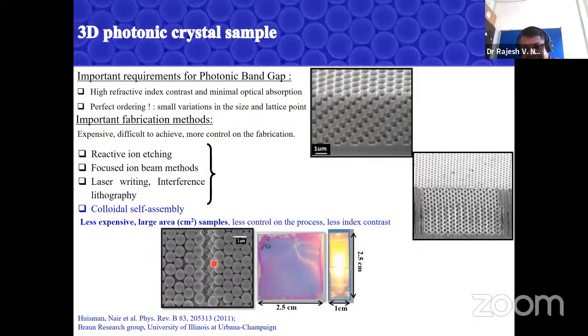This is what a laboratory sample looks like after your growth. If you're lucky and good at growing the samples, one can grow a sample in 1 week's time, and you can see nice diffraction. The color you see is because when you shine white light, the light is reflected back to you because of diffraction, since that light is not allowed to propagate into the system. This is exactly what happens in a peacock feather. When the sunlight hits it, different colors are reflected according to the periodicity of the different barbules in the peacock feathers. And I'll show you one of the measurements we did in our lab to confirm this kind of resonance from natural systems also.